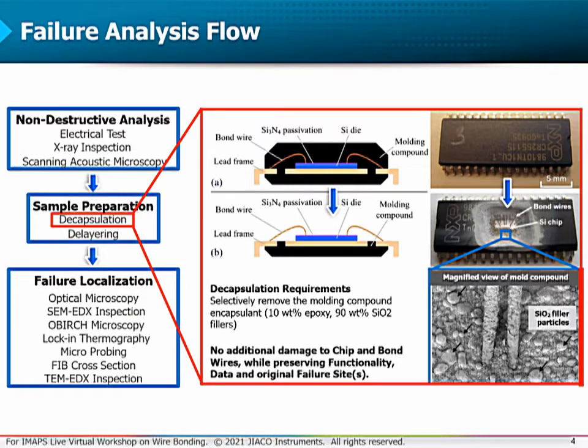Decapsulation actually represents selective removal of the molding compound, which consists of 10% epoxy and around 90% silica fillers. Due to the limited amount of samples and time pressure, reliable decapsulation is a prerequisite in field returns. The decapsulation requirement is the preservation of the following elements: metal bond wires, bond pads, silicon die, functionality, data, and also original failure sites. All this is absolutely necessary so that reliable analysis is performed afterwards.